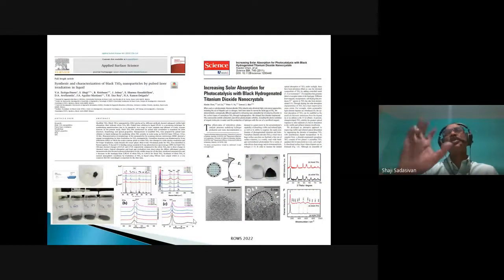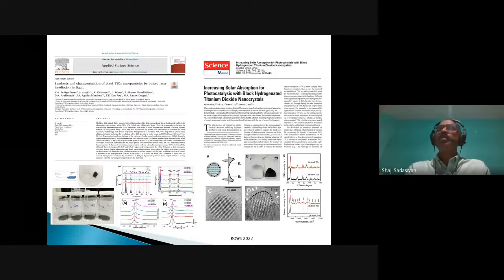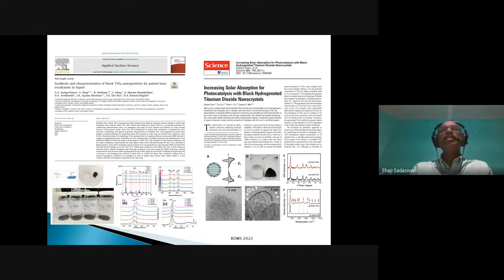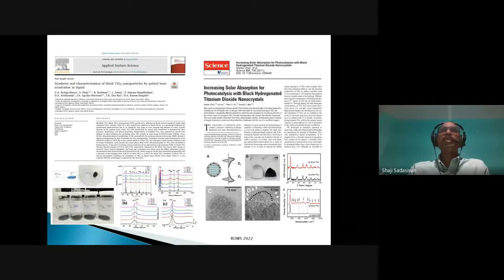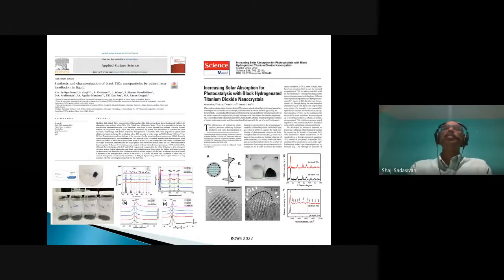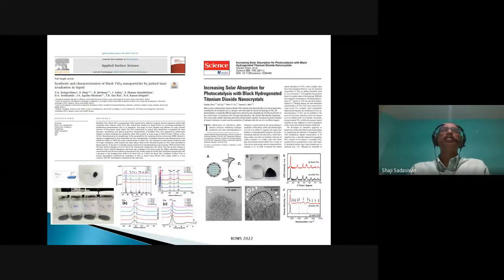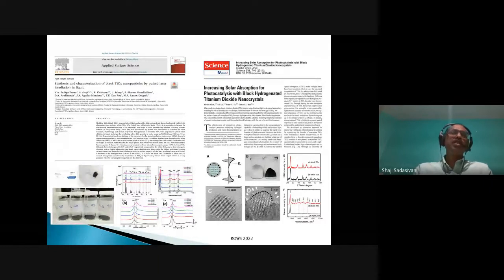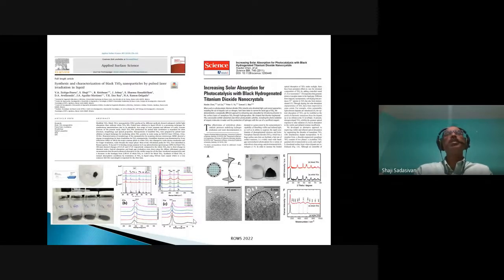We published the article in the Journal of Applied Surface Science. Our article alongside the first paper on modified or black TiO₂ — reported by a group from Lawrence Berkeley National Lab and UC Berkeley in Science in 2011 — where they used hydrogen reduction or hydrogen plasma for hydrogenation at high temperature and long duration to convert white TiO₂ to black TiO₂. In our case, we did it under normal conditions by irradiating TiO₂ powder dispersed in water for 45 to 90 minutes, and we got very stable black TiO₂ — those samples are still stable in the lab.